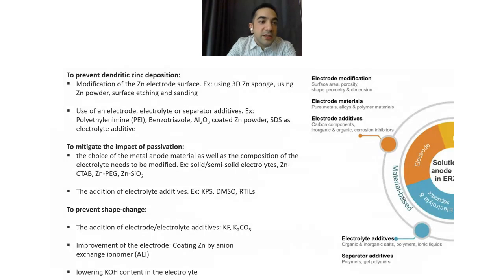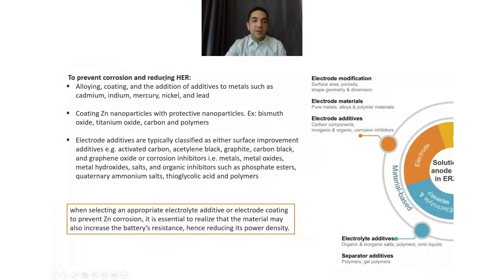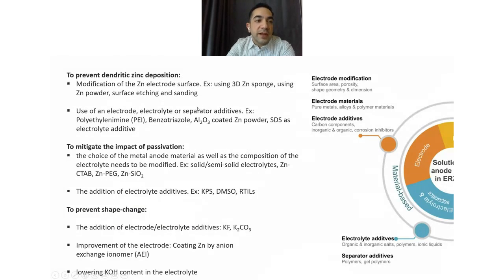They're mostly focusing on four different aspects. One is to prevent dendritic zinc deposition, also to eliminate the passivation, to prevent shape change, and also to prevent corrosion, and the corrosion is a matter of hydrogen evolution reaction. So to prevent the dendrite, you can modify your zinc surface, for example, instead of using a solid and smooth surface, you can apply a 3D zinc sponge or use zinc powder instead, or apply some surface etching and modifications. Also, you can use additives to the electrolyte, electrode and separator like PEI, coating your zinc powder with aluminum oxide, with sodium dodecyl sulfate, and to the electrolyte, and this kind of strategies.